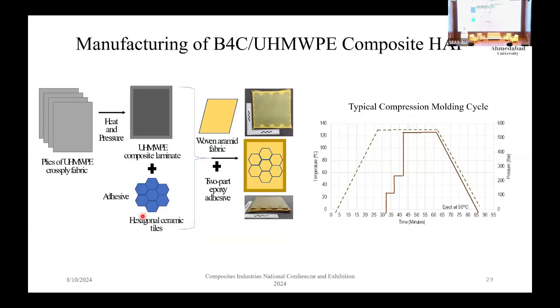Now, how to integrate ceramics with UHMWPE. In one of the images we have seen that if the ceramic plate is integral, that is one piece, or what we call monolithic ceramic, then one bullet is sufficient to generate cracks till the end. So what we did, we took 30 mm hexagonal or 30 mm square tiles, so that when a bullet hits, only a small group of maybe 1 or maximum 7 tiles, that is 1 at the center and 6 touching it, will be damaged. The other sides are at least safe.